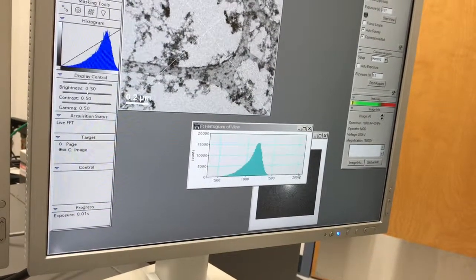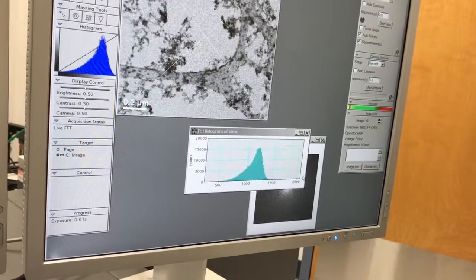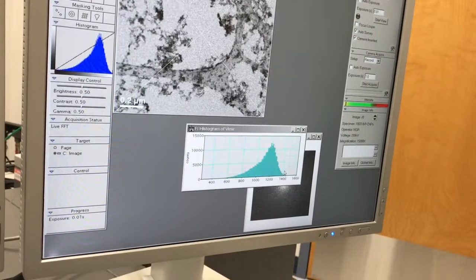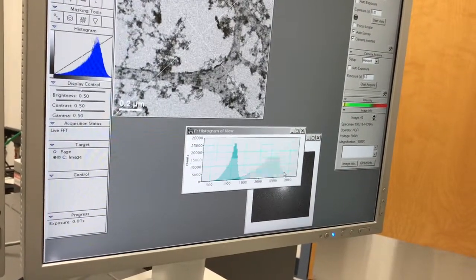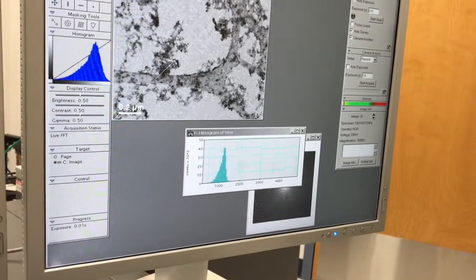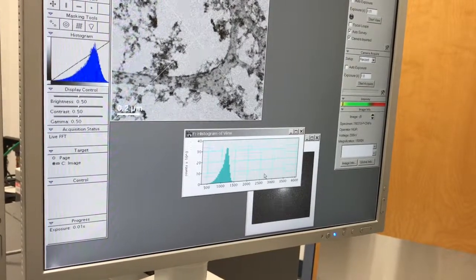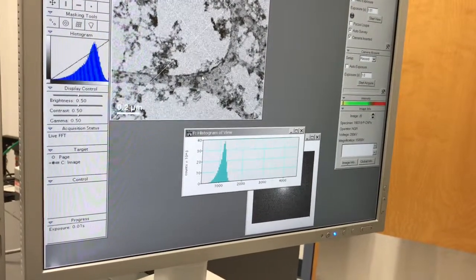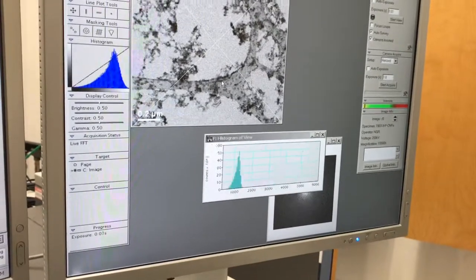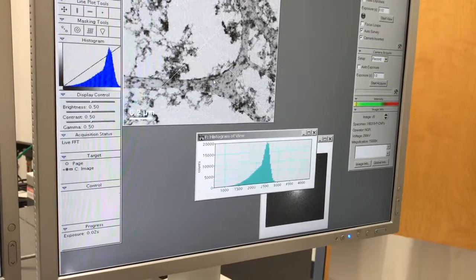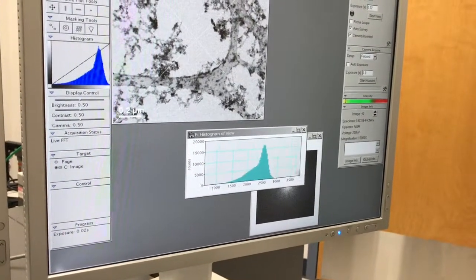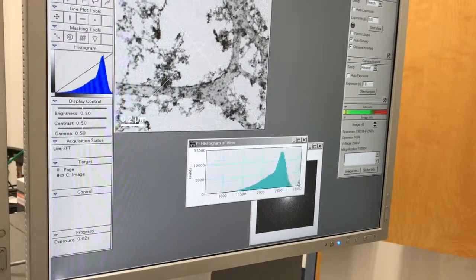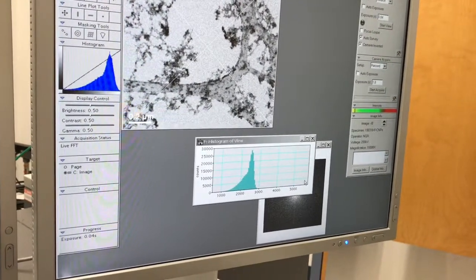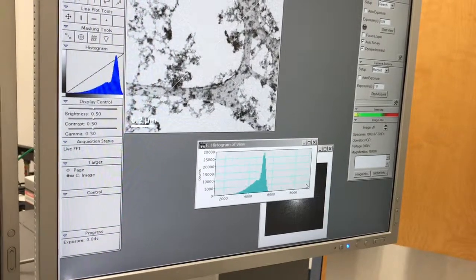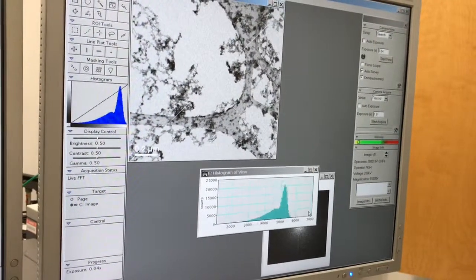It's a little hard to see that right now because I have a low signal to noise ratio here, which is why you're seeing this histogram oscillate all over the place. So you see less oscillation. If I double it now, you can see that even though this is oscillating, this max value went up. I double it again, max value goes up again. My signal to noise improves.